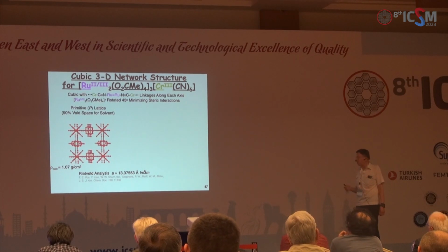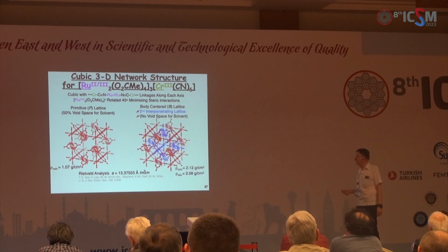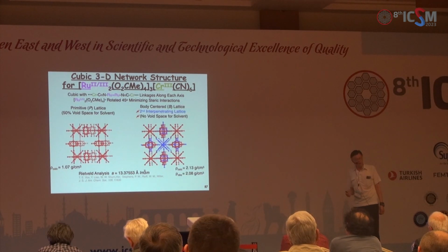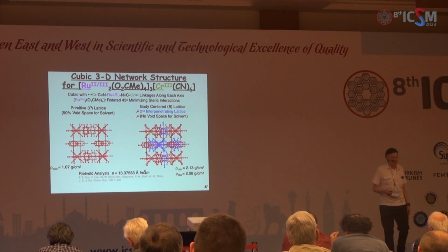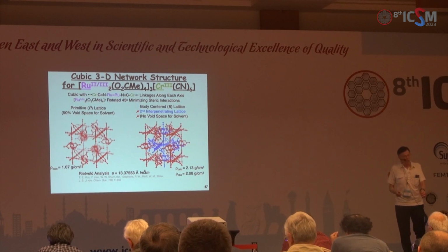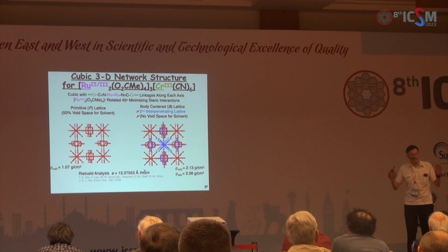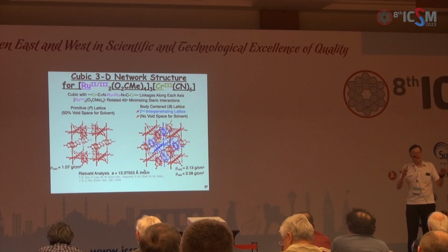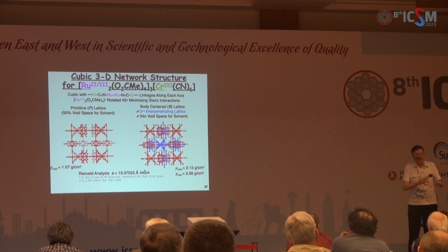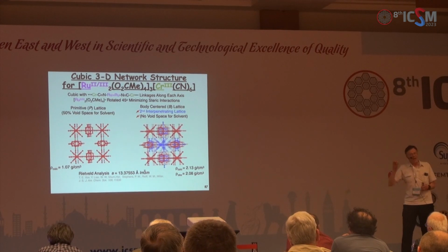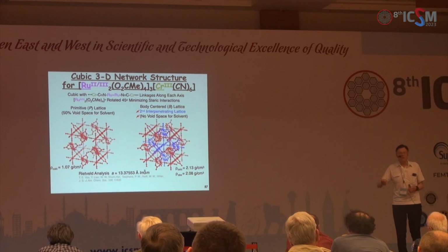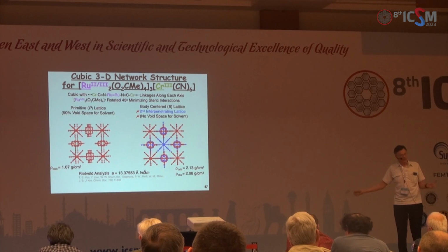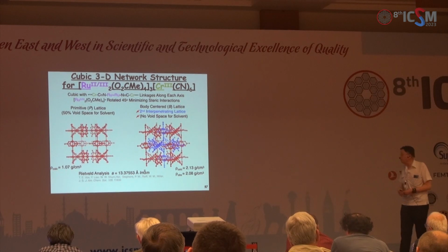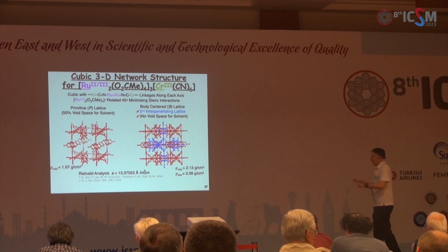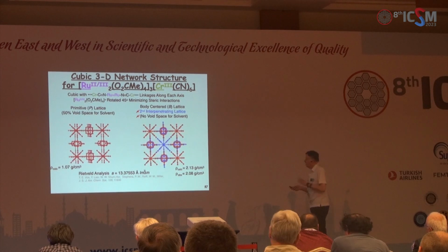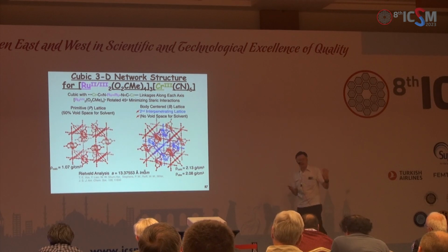To make it body-centered, we have to put another chromium in the center of the unit cell, and that chromium has an identical lattice to the red lattice, colored blue, showing there are 2 interpenetrating lattices with no chemical communication through bonding between each other. If you're an ant walking on the blue lattice, you'll never get to the red lattice—they're just not communicating that way. Of course, we solved the structure from powder diffraction and verified the density; it has this structure.